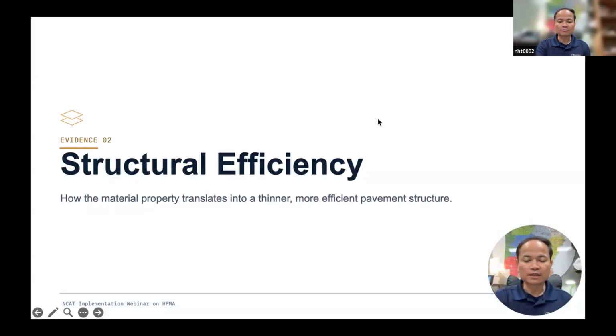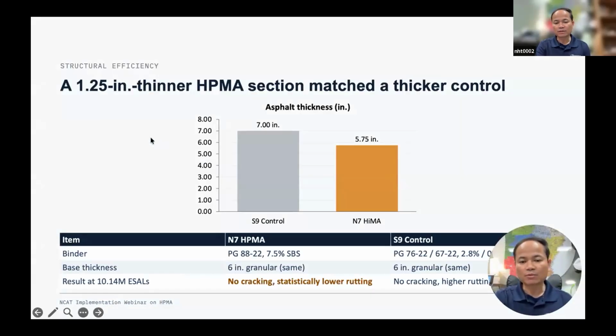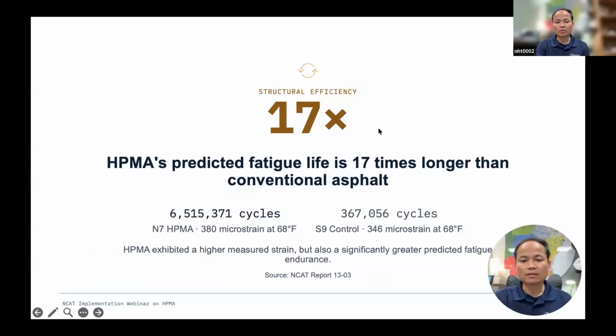So the next section that I'm going to do here is that Dr. Tim, looking at all the data, also did the structural analysis and saw how section N7 performed compared with section S9 control. You can see here in the 2009 research cycle, we had section S9 with 7 inches of asphalt, and section N7 with 5 3/4 inches of asphalt, which might be HPMA in that cross section. Now, what we found is that for the cracking resistance, or the fatigue life of that section, from the graph that Nathan showed earlier, the predicted fatigue life for that HPMA N7 section is 17 times greater than the predicted fatigue life for the S9 cross section.